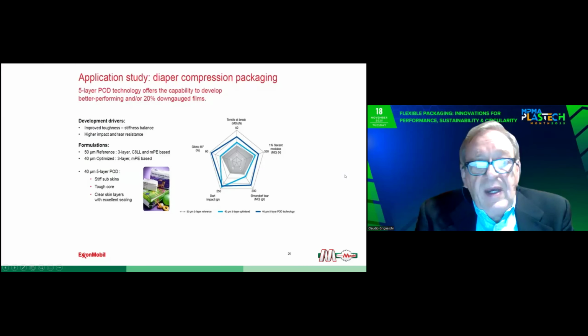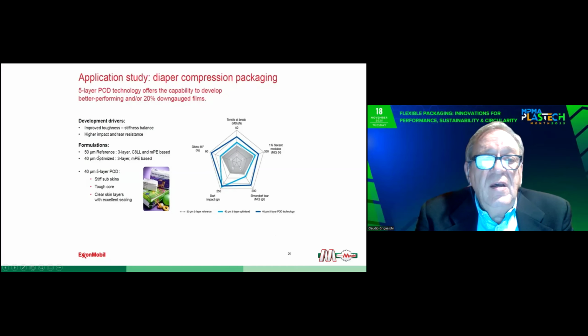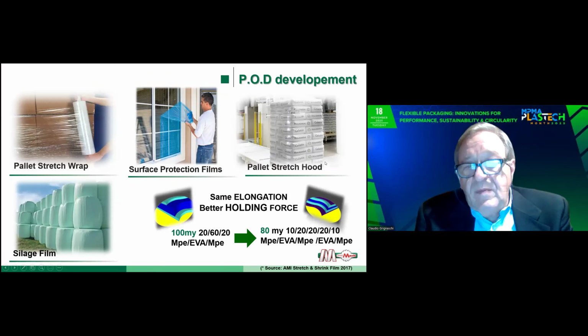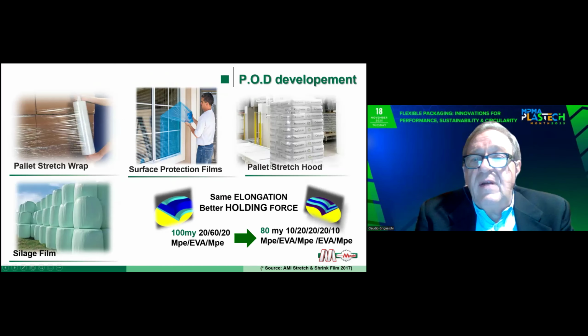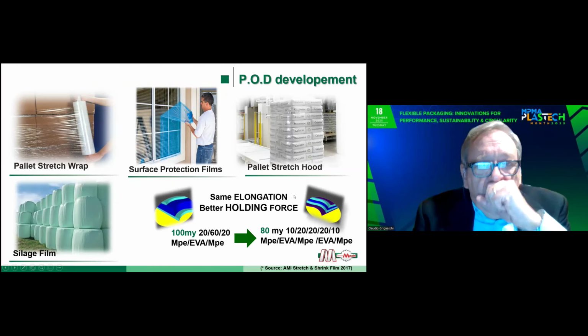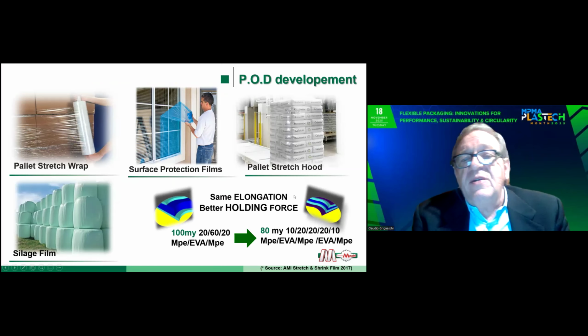Diaper compression packaging—this is a study carried out by ExxonMobil, and as you can see, there's a decrease of 20% in thickness, from 50 to 40 micron. Pallet stretch wrap, for instance, allows you to decrease stretch wrap thickness from 100 micron to 80 micron, with the same elongation characteristics and a better holding force.